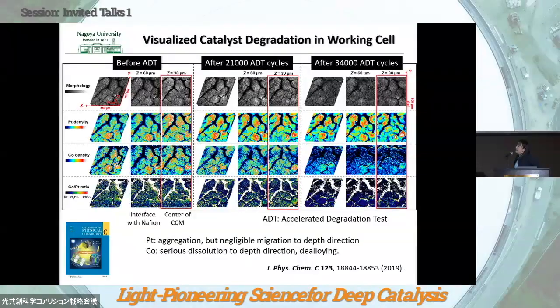And on the other hand, you can see the large decrease in the cobalt density due to the accelerated degradation test on the PEFC. So they have a completely different reaction mechanism for the degradation of the alloy catalyst. Cobalt species seriously dissolved due to the reaction of the MEA, and the dealloying of the catalyst proceeded under the working conditions.